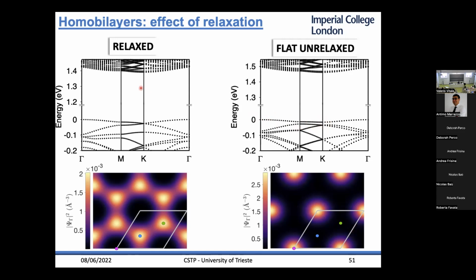But if you do relax the system, then the band gap at K closes and you have this linear dispersion. And if you plot the wave functions at gamma, then it has more of a hexagonal emergent lattice. So we didn't start with either of these two lattices, but then the Moiré patterns generate these states.